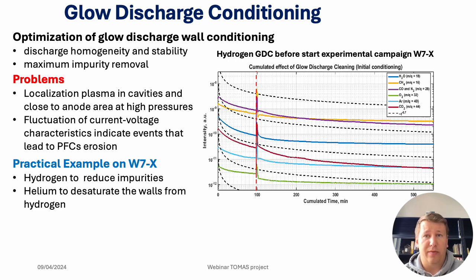You can see an example of hydrogen glow discharge cleaning in Wendelstein 7-X. The dominant impurities such as water, methane, and carbon oxides are significantly reduced in the residual gas content during the glow discharge application. Additionally, it's worth noting that every impurity removal rate follows a certain exponential time trend. As a carrier gas, helium is more effective for fuel hydrogen removal from the walls.